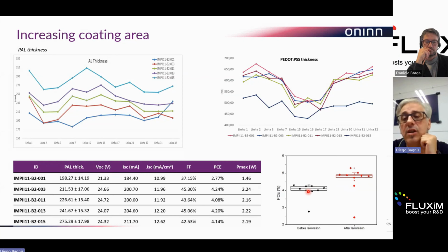But you see that for the production line, we try to optimize after the lamination, because we want a higher performance after the lamination. So everything is set not to get the best performance before the lamination, but after the lamination, as shown here.